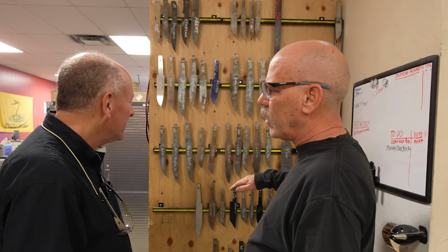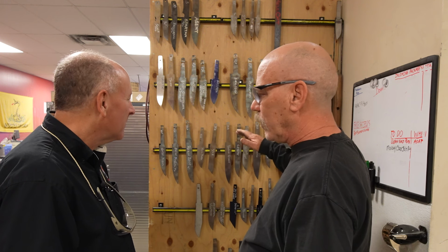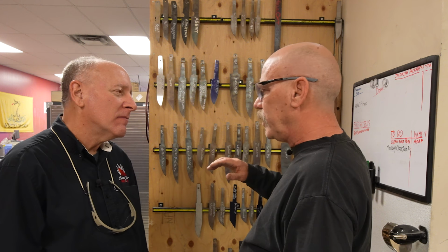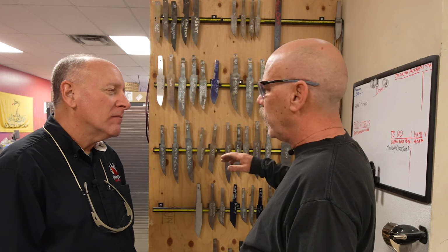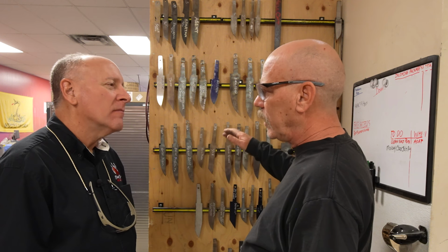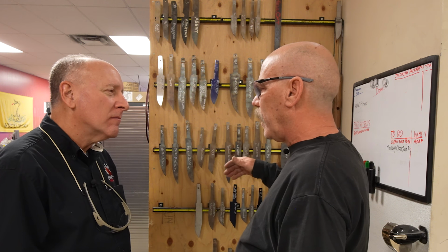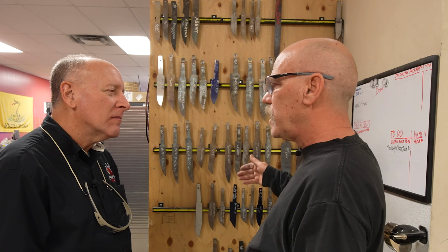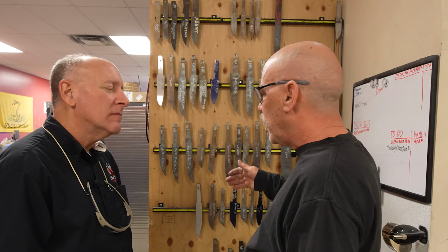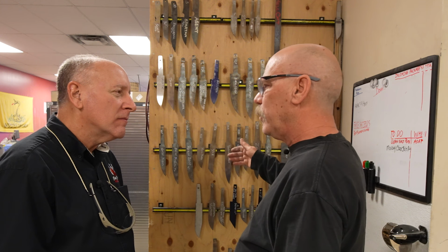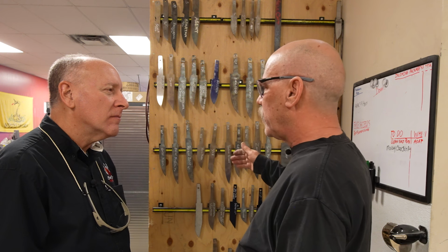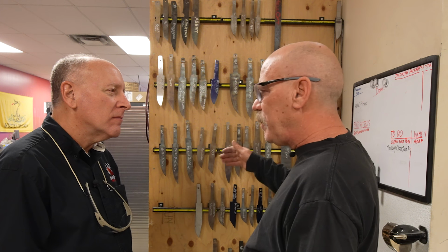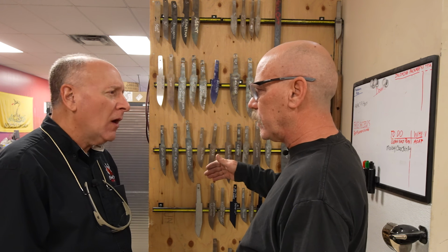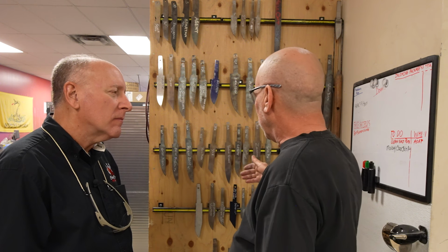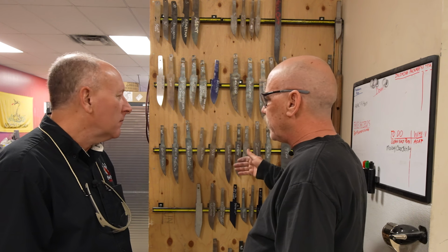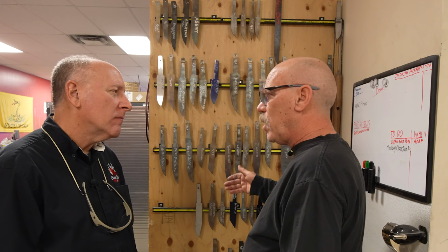This is all precision ground flat stock. It's completely decarb free when we get it. It's ground size and shape, and it's completely spheroidized and annealed. So it's in the optimal condition for cutting it out and grinding it. And then we have a very cautious heat treating process here, so we know exactly what's going on with the steel. The heat treat on any given steel is every bit as important as the quality of the steel. Absolutely. And when I'm selectively tempering this stuff, again, it's a very cautious process.